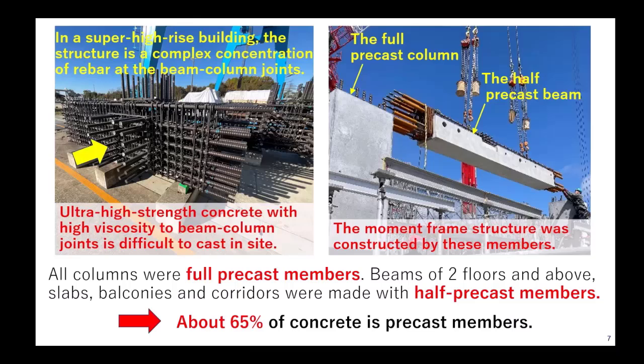In addition, beams of 2 floors and above, slabs, balconies, and corridors were made with half precast members. As a result, about 65% of concrete is precast members. So we achieved a 5-day cycle per one reference floor. If concrete was cast in place, it took about 20 days. Not to mention, the formworks of concrete members were greatly reduced.